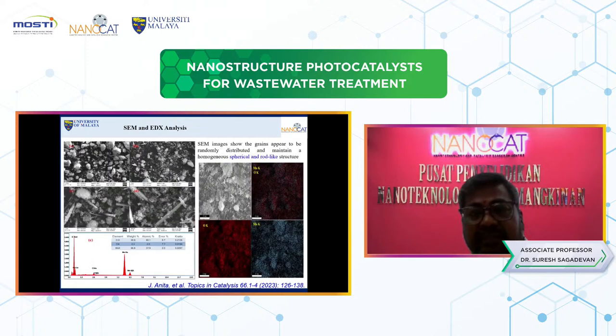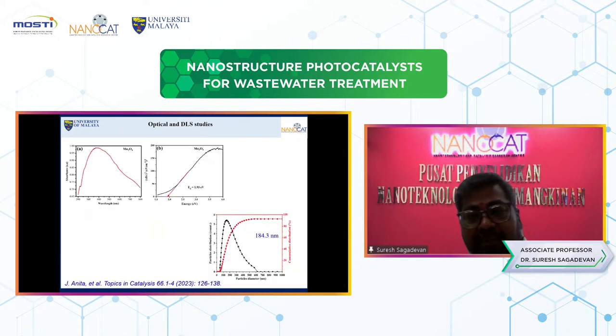And as well as you look at here, when you go for different magnification, you check how the morphologies change. Initially, A and B represent the magnification of 10 micrometer and 2 micrometer, showing a particular shape of morphologies. When you change the magnification, we observe rod shape morphologies. And as well as Mn3O4, which is confirmed for purity, there are no other peaks present, which is confirmed from the EDX analysis. And as well as the presence of Mn and O by EDS mapping, which confirmed the purity of this prepared sample.